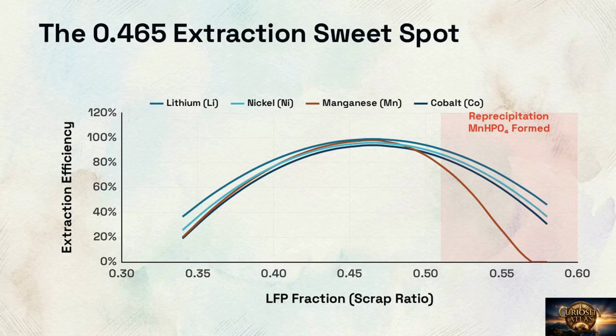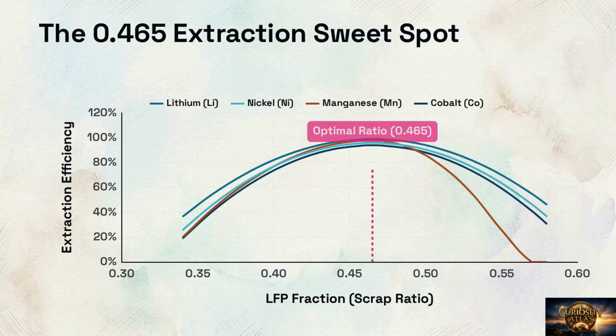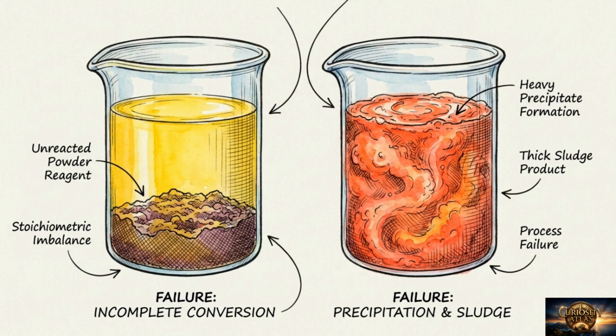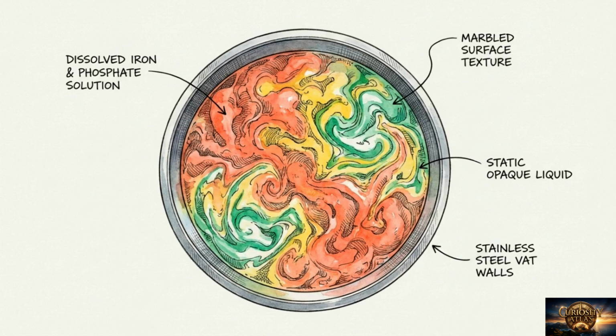This happens because an excess of phosphate forces the target metals to reprecipitate into solid compounds that fall back out of the solution. The optimal ratio is exactly 0.465, where the extraction is maximized but the phosphate levels remain below the precipitation threshold. Reaching these peak yields is a matter of strict stoichiometric optimization, balancing the necessary iron against the dangerous phosphate. Even at the optimal ratio, the iron and phosphate are now dissolved in the liquor and must be removed to purify the target metals.